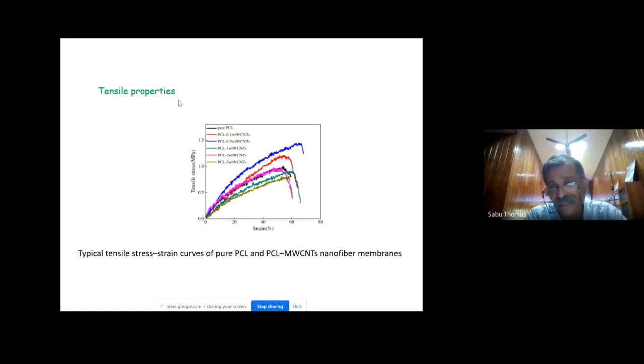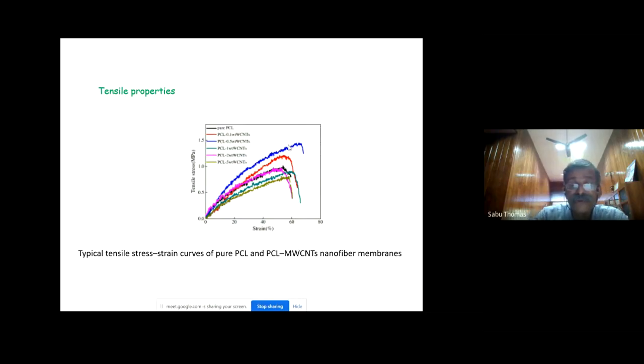Let me show you another important property. When you use any polymers for tissue engineering application, the system should have good mechanical strength. I will show you one slide. This is pure PCL, the black one. PCL doesn't have very good strength and modulus. If you just put 0.5% of multi-walled carbon nanotube, look at the blue one. The modulus increases, the strength increases. Therefore, dear colleagues, adding a small amount of nanostructures can increase the mechanics, because the scaffolds have to be robust. But don't ask too much. If you have too much nanomaterial, the mechanical properties decrease.